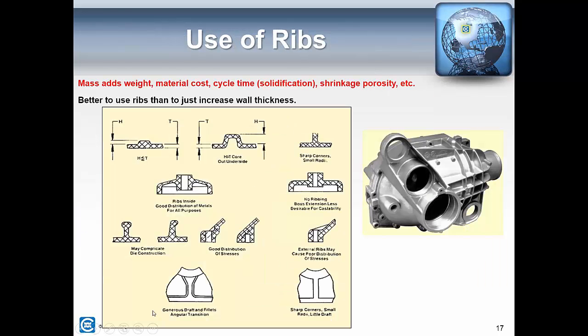These are some of the ribs that I talked about in the previous slide. In the top left corner, you can see that if you have a slightly smaller rib than the nominal wall thickness, generally that doesn't cause too many problems. But in the top middle view, the H value is much greater than the T value. That would be a time where you'd want to core out underneath where that rib is standing out.